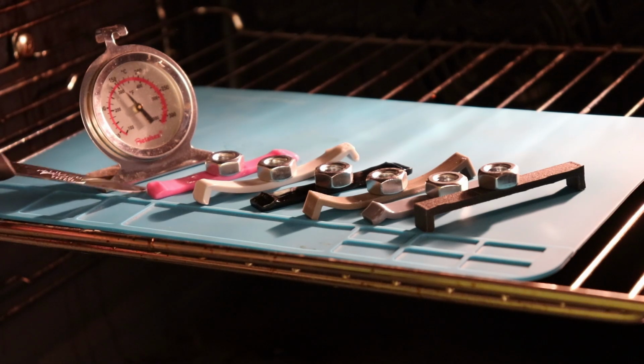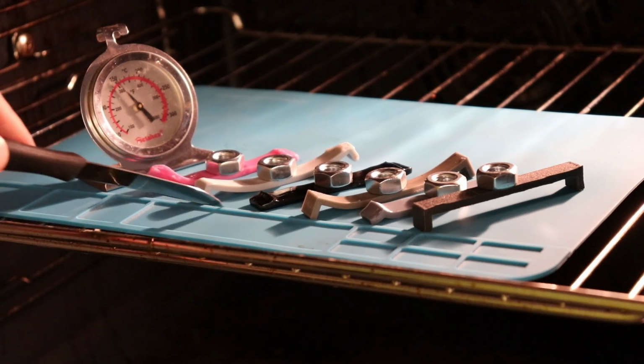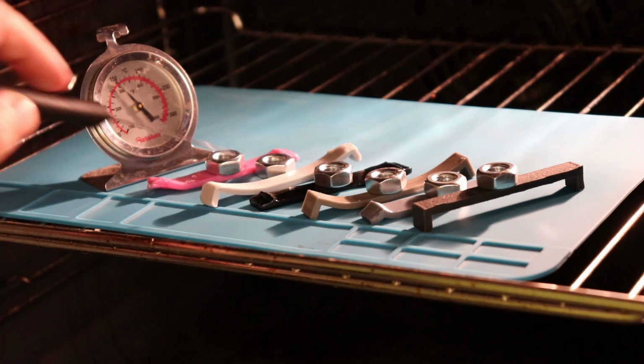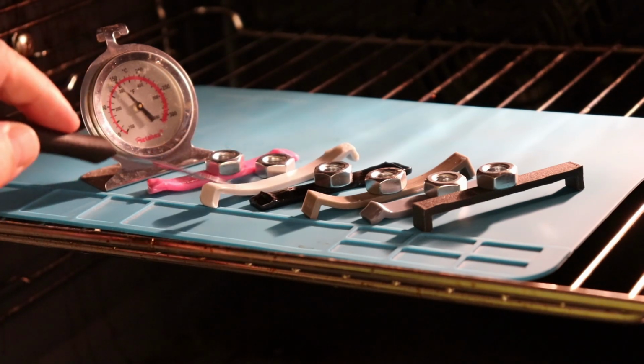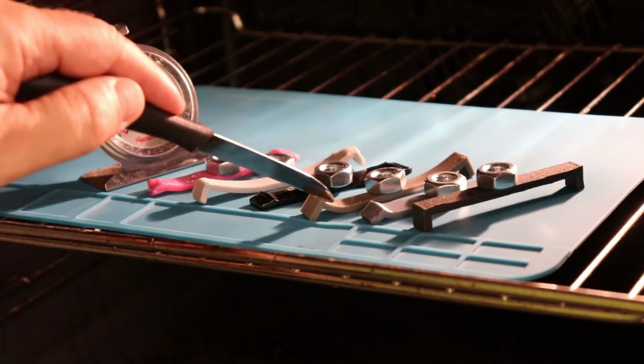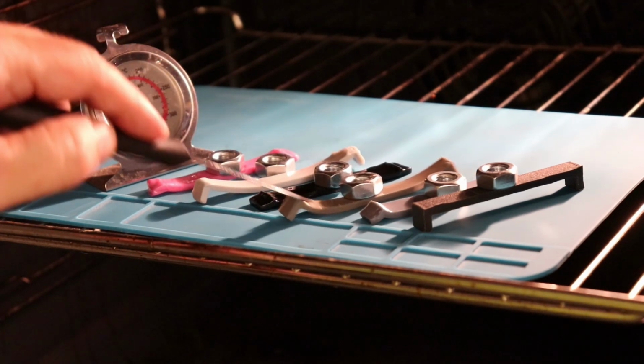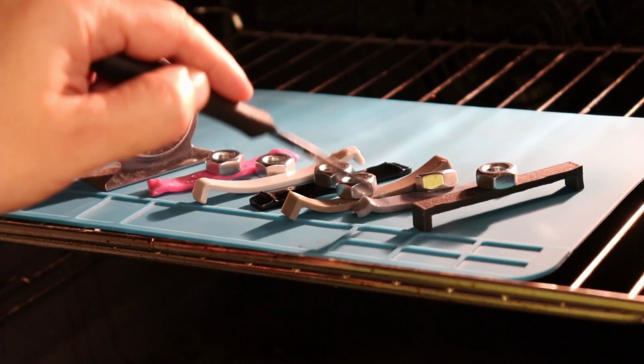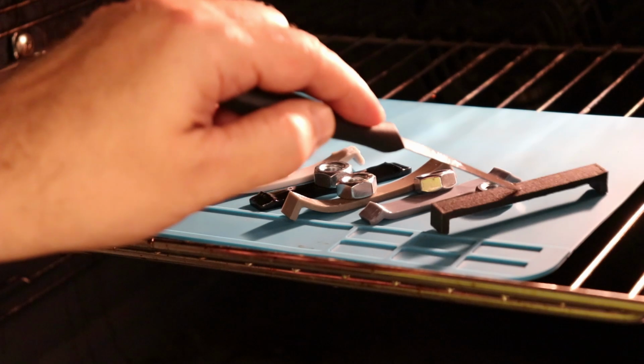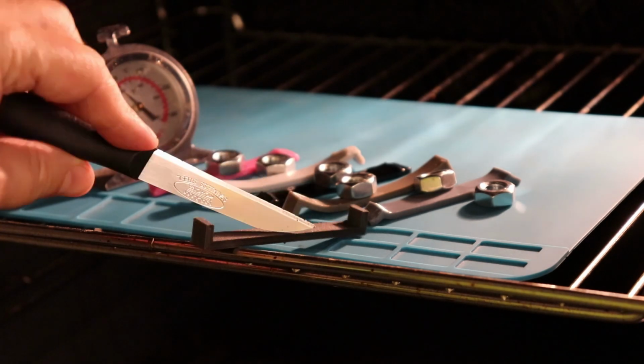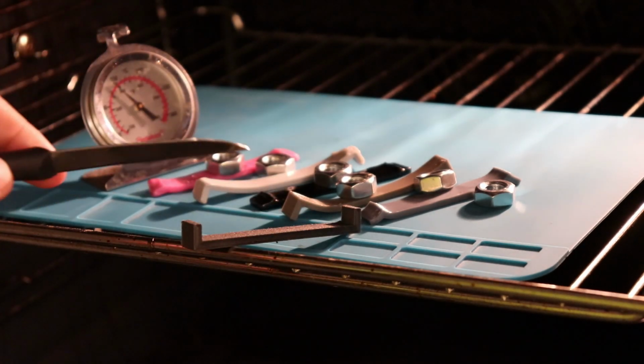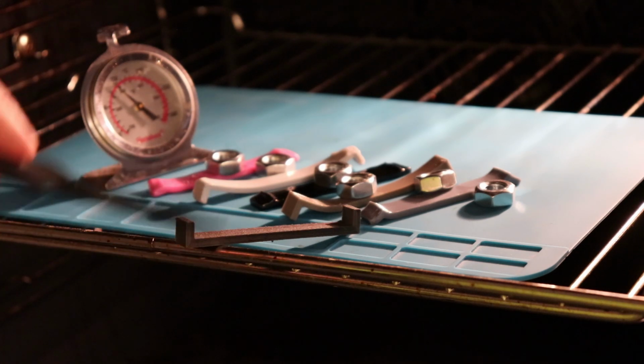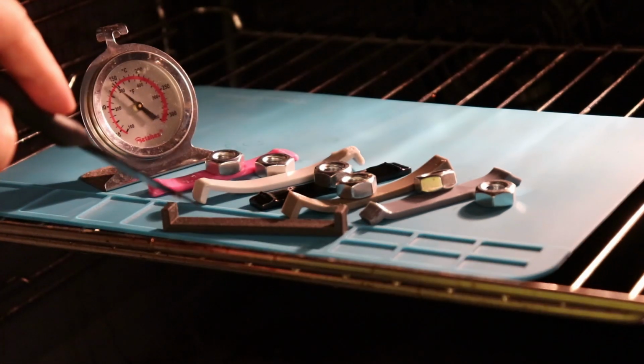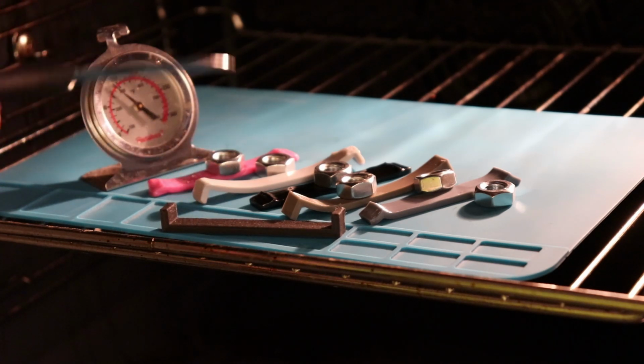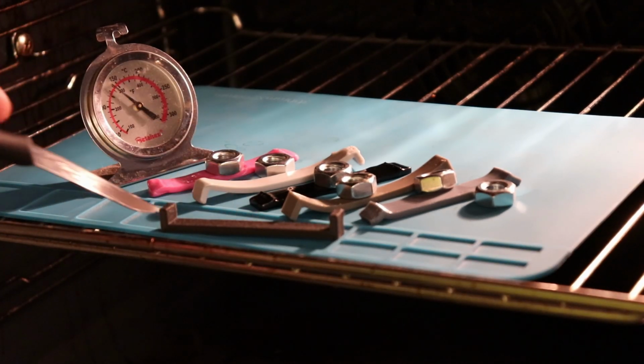Quick analysis. Well, this I have to pick up with the spoon. Okay, this is very melted, and the PETG, silk is, well, of course melted, but so was this TPU, and also the ABS is soft. And look at this. Okay, it's a little bit soft. Let me try to. Oh, it's too hot yet. But it's quite hard. So almost 160 degrees Celsius. It didn't start the deformation, and it's quite hard. That's not the carbon fiber the reason, but the nylon as base material.